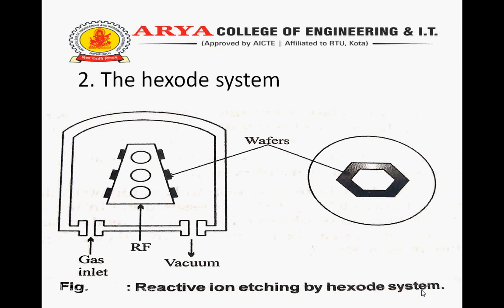The etching rate of undoped silicon is very low in chlorine or Cl2 ambient if ion bombardment is not present. Heavily doped n-type silicon or polysilicon etches at high rates without bombardment if Cl, meaning chlorine, is present, but not in the presence of Cl2, chlorine molecules.